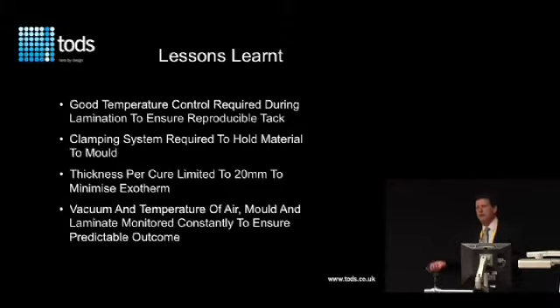Because of the relatively low temperature cure, these materials are quite lively exotherm-wise, so we minimise the maximum thickness of cure at any one time to 20 millimetres. And also you need to check the temperature, vacuum of the mould, air and the laminate constantly, and particularly the vacuum in several places. Because it's such a large structure, you can be measuring the vacuum on one side of the dome, and at the other end you've actually lost vacuum through a leak. So we constantly monitor, we have people there monitoring during the cure process, and if necessary, particularly at a lower temperature, if you get a leak, they go in and fix it.